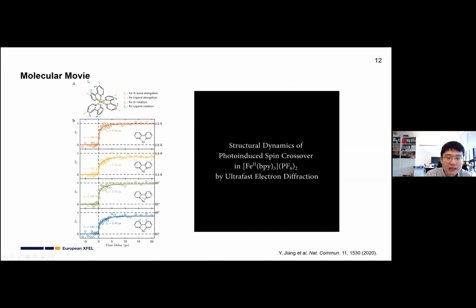In order to get the molecular movie, for this work I set four key structural dynamics groups. One is iron-nitrogen bond elongation only, one is iron-ligand elongation, then the nitrogen-iron-nitrogen angle rotation, and also the ligand rotation. When we do the principal component analysis, I can know the contribution of those structural components at every time delay. It's important to notice that for the local iron-nitrogen bond elongation and structure change, they can all reach almost 100%, like people suggest in the solution. However, for the ligand, they never reach that much compared to what people suggest.